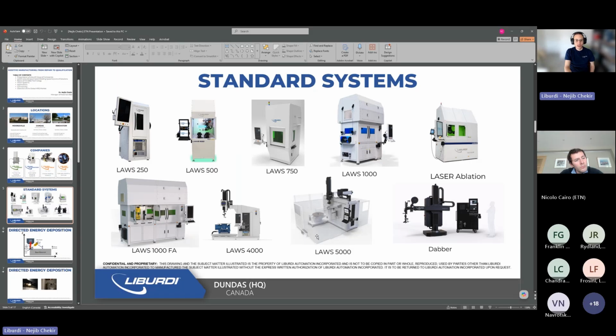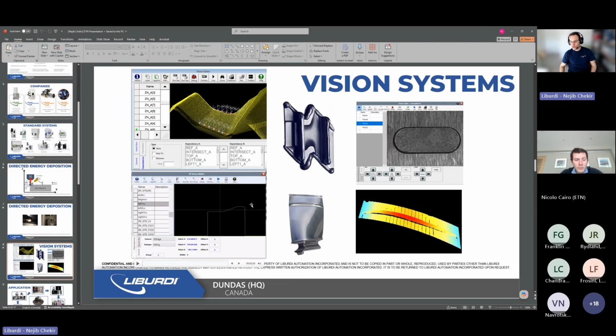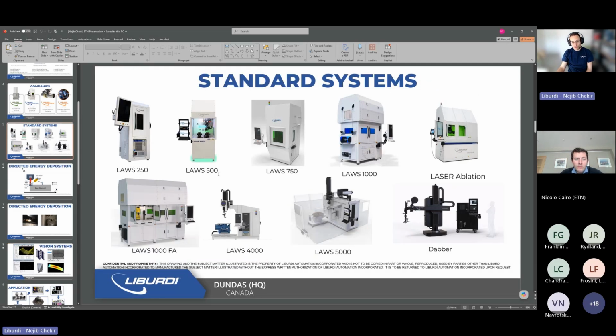the micron precision. Combined with the vision technologies that I described earlier, which can also generate very precise sights based on a calibration procedure that we developed to relate the data from this vision technology to the gantry position, you can achieve highly precise positions. That's to understand where to shoot your laser and feed the powder or the wire.